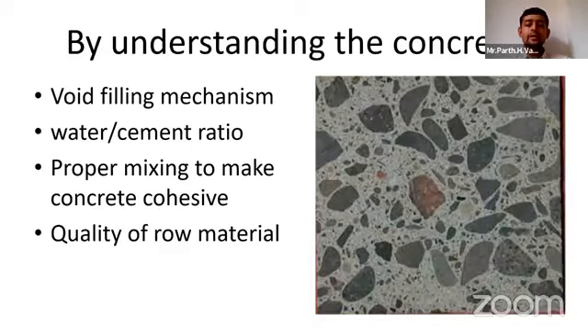In case of raw material, sand also plays a very important role. Cement is a binding material which binds all the aggregates from their surface. So if sand has more silt content, the surface area will increase, and the greater the surface area, the lower the strength of the concrete will go. We cannot see in fresh concrete what the content of silt in the sand is, but we have some methods to figure it out on site, which I will show in one video later.